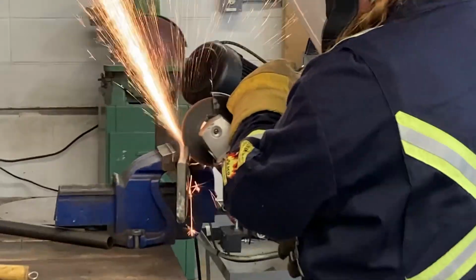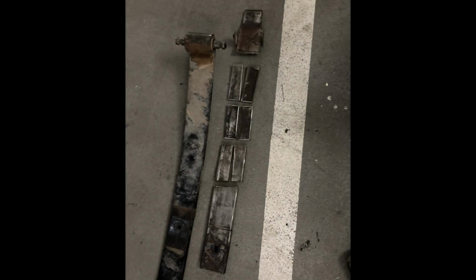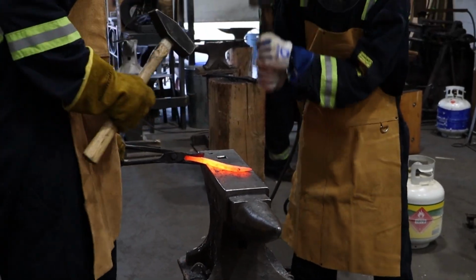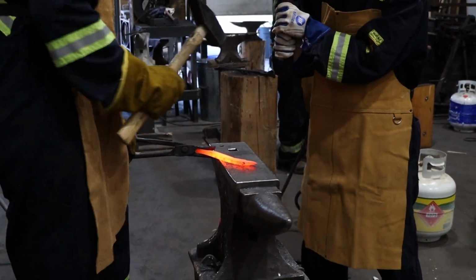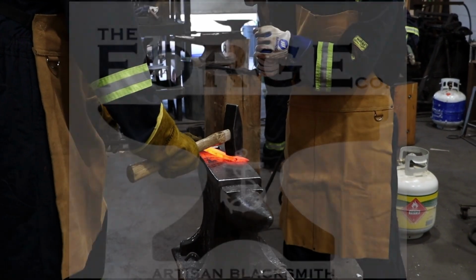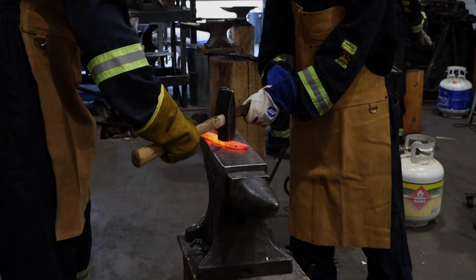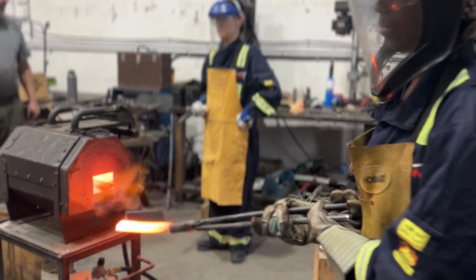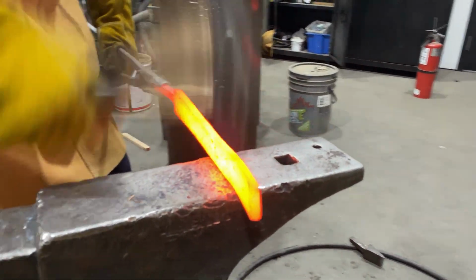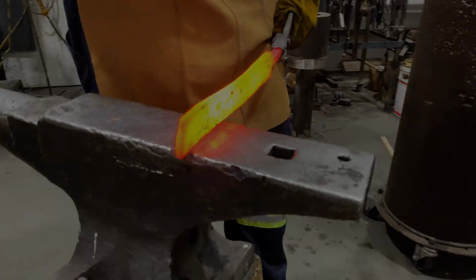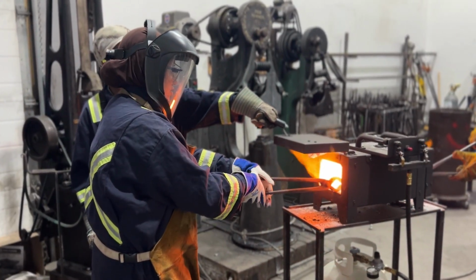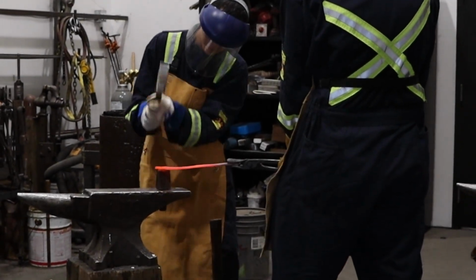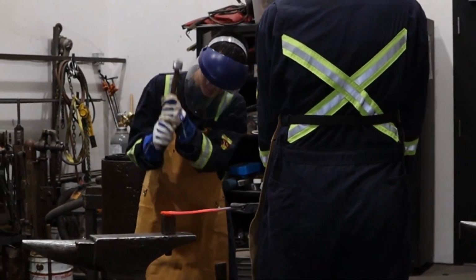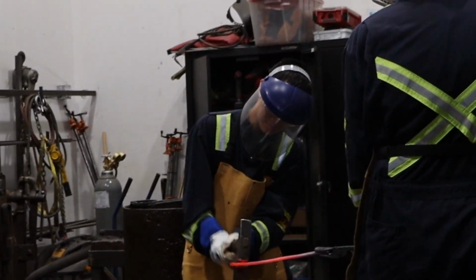And now we will explain the blade making process. We began making the blade by cutting our raw leaf spring into workable billets. Next, we hand forged these billets at a local blacksmithing company named Forge Co. at 1300 degrees Celsius over a span of 5 hours using a gas furnace. Forging was done by hammering the billets at intervals of approximately 30 seconds before returning these billets back into the furnace. We also hot cut the end of the billet at a 45-degree angle, which is a traditional Japanese bladesmithing